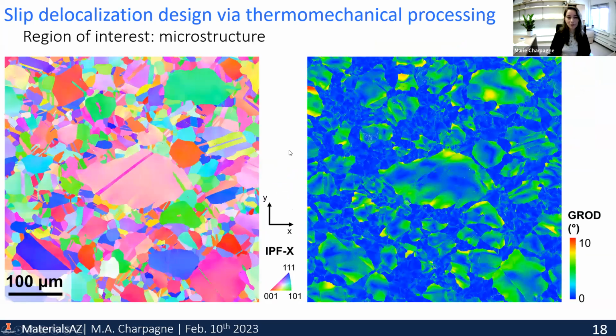All right, so we go back and take this microstructure and actually make a dog bone out of it and measure with high resolution digital image correlation. We measure our distribution of slip band intensity. So this is our region of interest. You can see we have this very large grain here in the center, a couple of others that are subject to very high lattice rotations, and then our second population of smaller grains that are more stress-free.